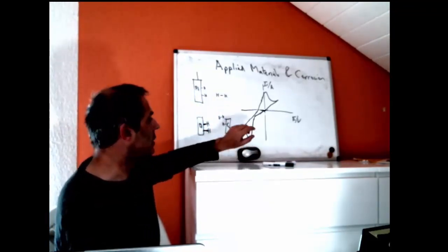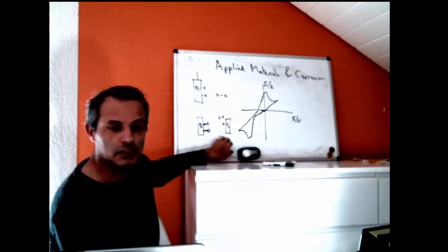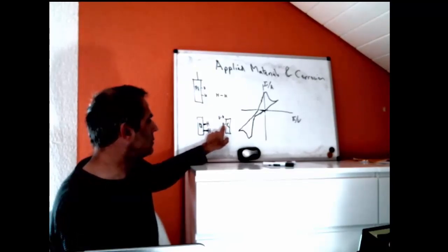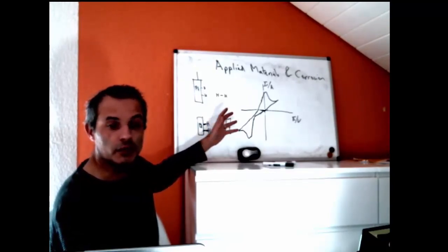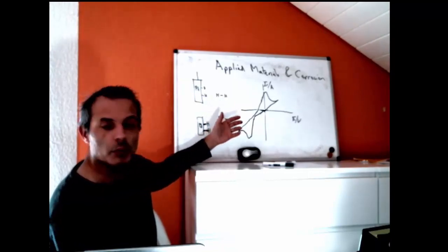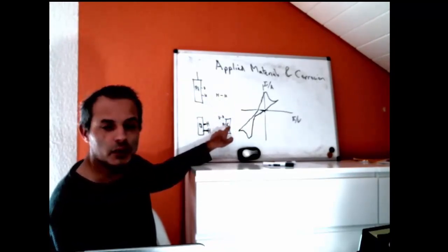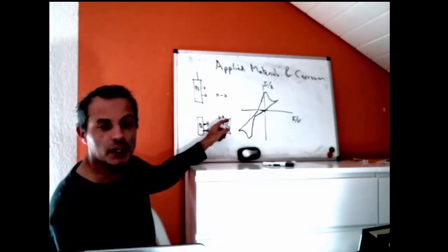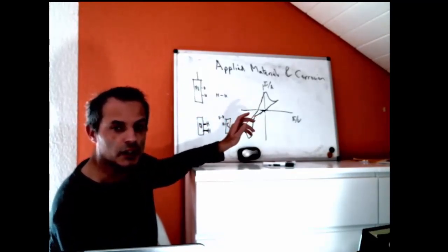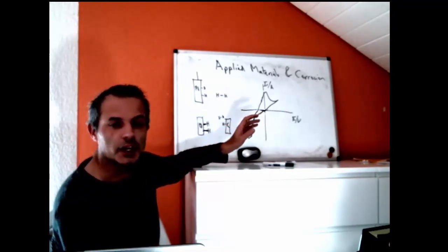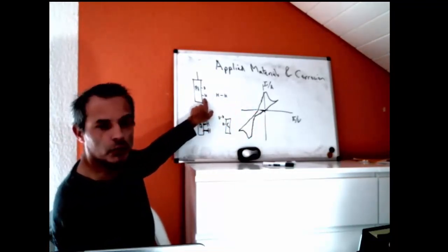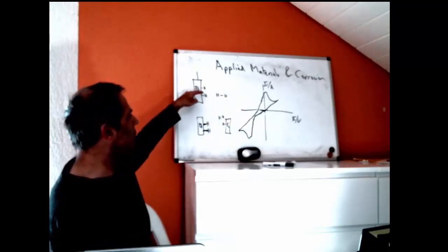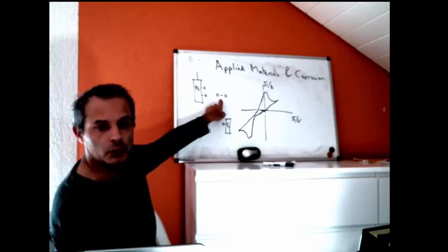We could make it weaker. So if we take an iron catalyst instead, we can make it weaker, but then the bond to the iron is very weak, and that means not very much of the hydrogen will break into hydrogen single atoms stuck to the iron. Most of it will hang around as a gas, and so it's not a very good catalyst either. Platinum just turns out to have a similar bond strength to hydrogen as hydrogen does to itself. So 2 of these is equal to 1 of these.